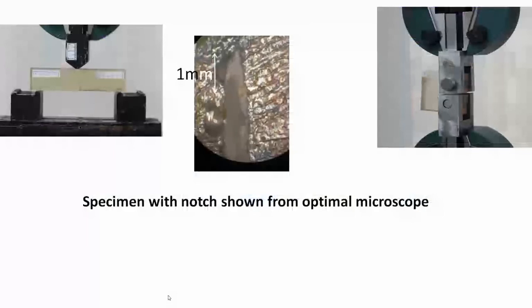To have a sharper notch for the crack propagation, we made a sharp cut with a depth of 1 millimeter with the help of a cutter. To ensure that no heat is induced to the crack area during the cutting by the razor blade, the cutting was done hours before the fracture testing.